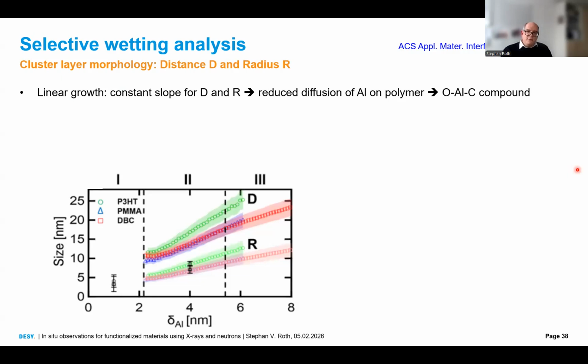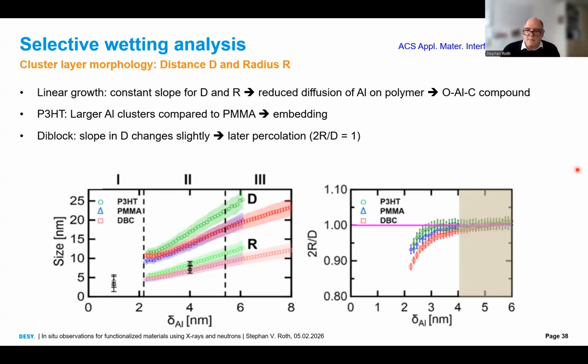We have a reduced diffusion of aluminum on the copolymer. We see a linear growth, not like we see a nonlinear growth for gold on polystyrene. We see an embedding. And now an important point is we can deduce for every one of our materials the percolation threshold. We plot here simply 2 times the radius divided by this. And when it's 1, the clusters touch each other, and we should measure electrical conductivity. And you see here that P3HT has a quite early percolation threshold.